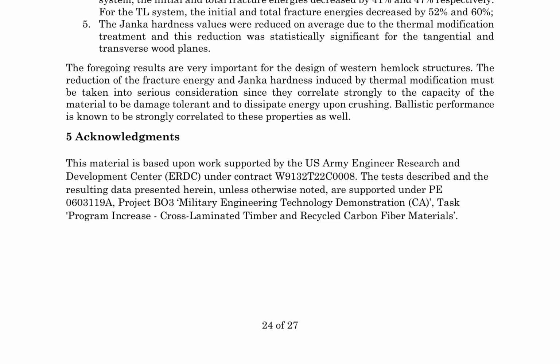4. The fracture energy of both radial-longitudinal, RL, and tangential-longitudinal, TL, systems shows a dramatic reduction due to thermal modification, with decreases of 41% and 47% in the RL system, and 52% and 60% in the TL system. 5. The Janka hardness values are reduced on average due to thermal modification, with statistically significant reductions on the tangential and transverse wood planes. These findings are crucial for the design of Western hemlock structures, as the reduction in fracture energy and Janka hardness induced by thermal modification must be taken into consideration.